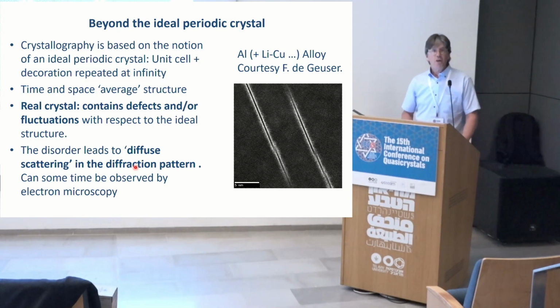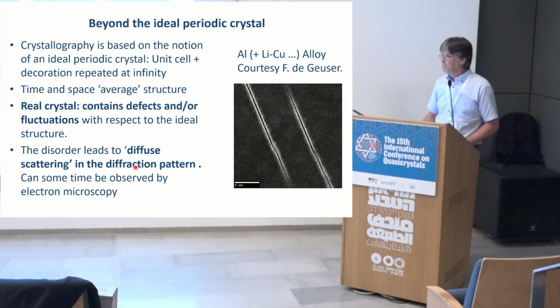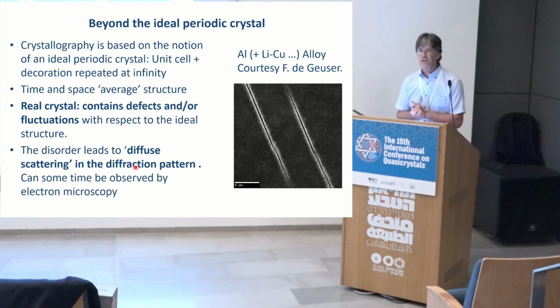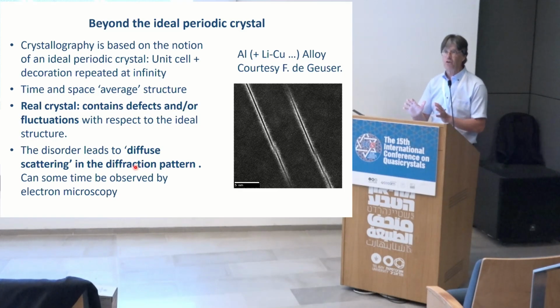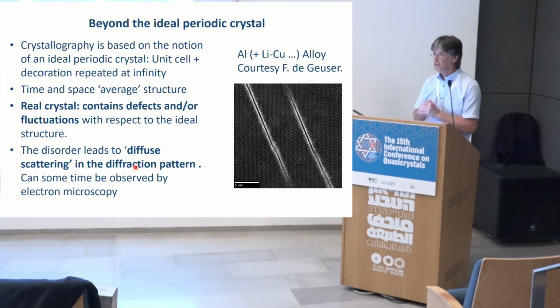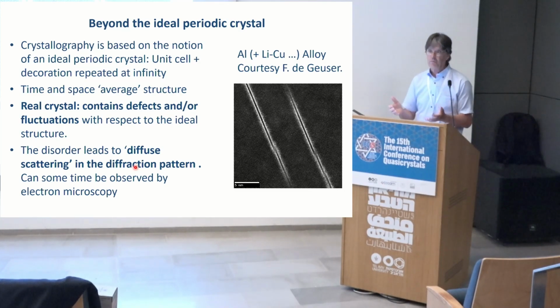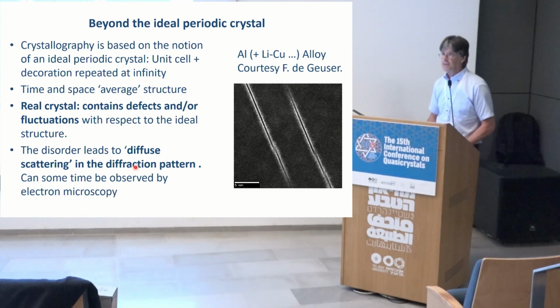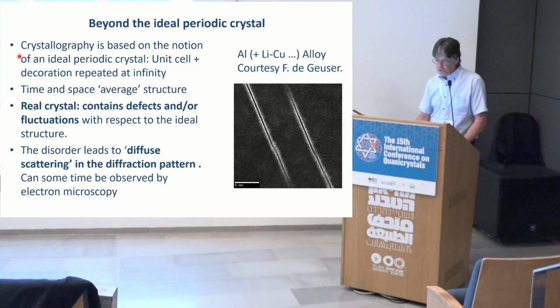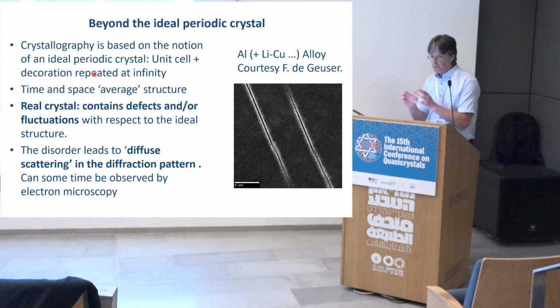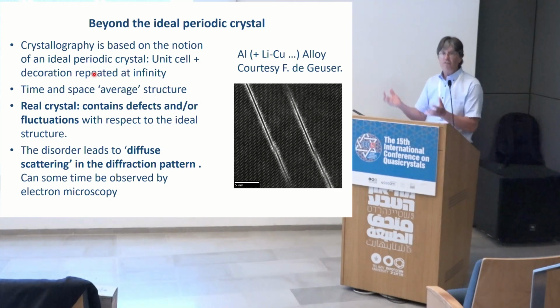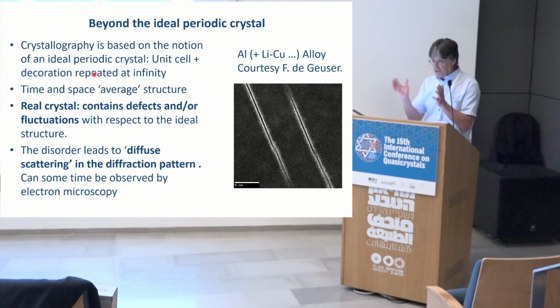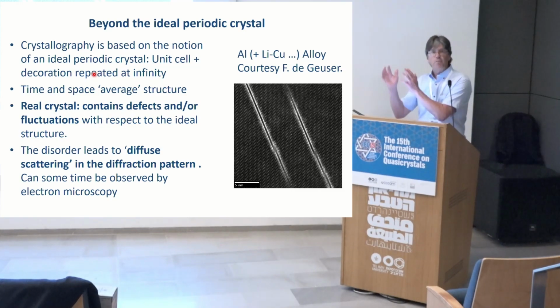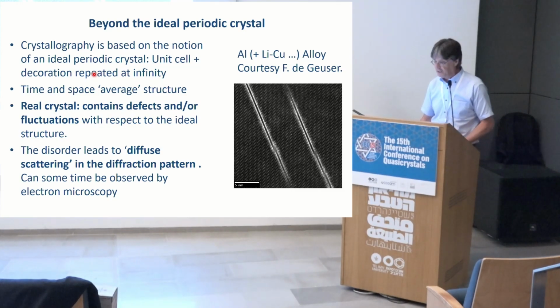But in real life, perfect crystals do not exist, or very rarely. Maybe silicon or germanium, that's the only one. All other materials we are using have defects inside. And this is very important, because tailoring the defects is a major tool in material science to tailor the properties. What you see with crystallography is just a time and space average of your average structure, which assumes that you have the same unit repeating at infinity, but we know that in reality it's not the case.